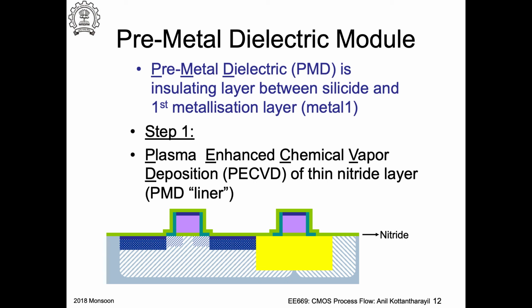Very important thing: beyond this point you can't do high temperature processes. Why? Because your silicide is already there, so there is already some metal on top. If I take nickel monosilicide, NiSi, formed on silicon source, drain, and the gate, and heat it to high temperature, in the range of 600 degrees centigrade, it would react with more silicon, forming NiSi2. But then the contact between that NiSi2 and silicon is not good. So any process that I use after forming the silicide should not be high temperature. You would like to keep it much below 600 degrees centigrade.